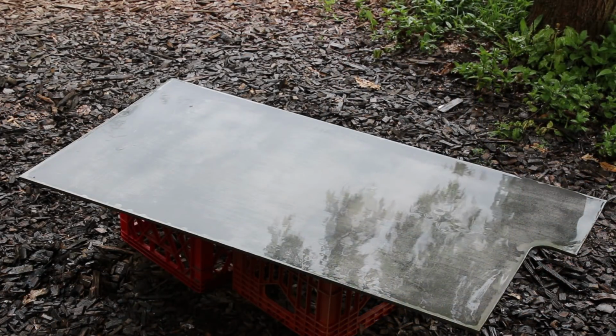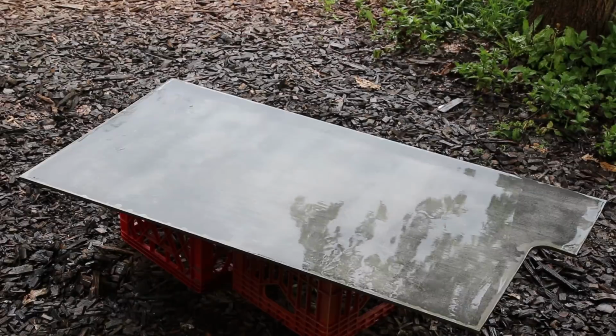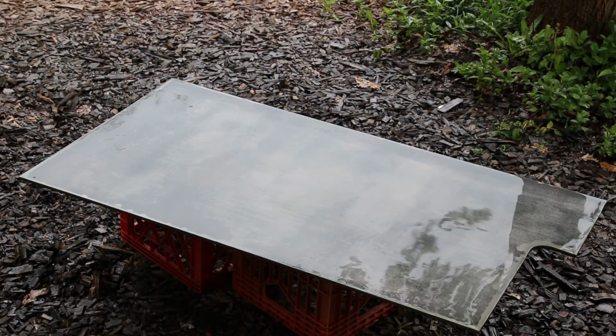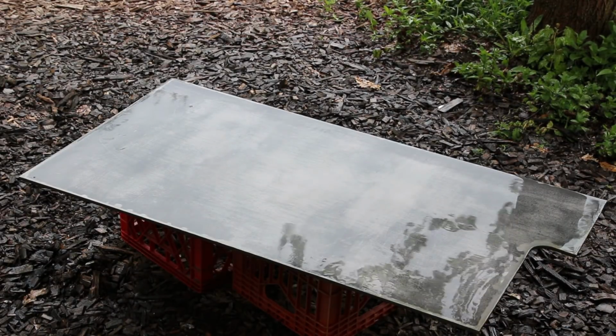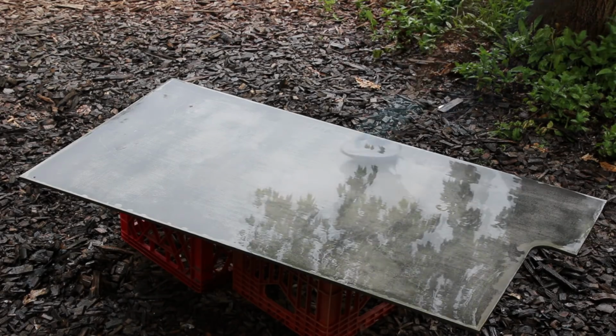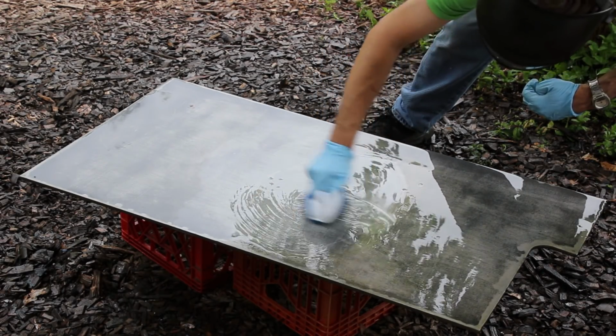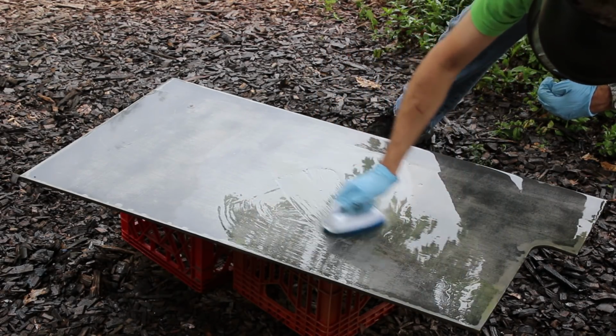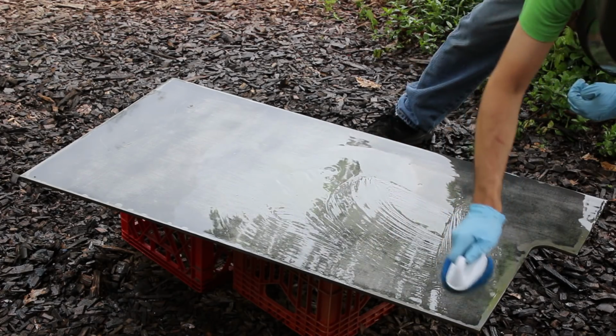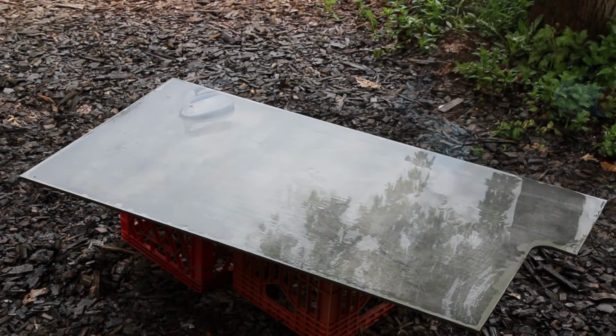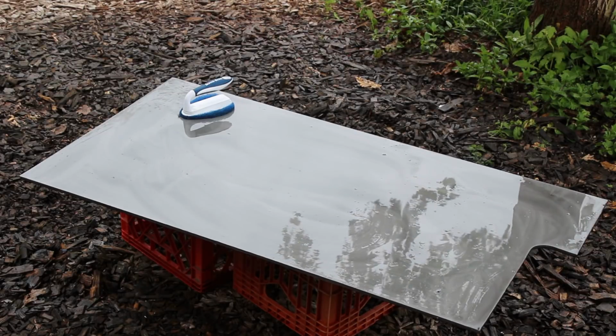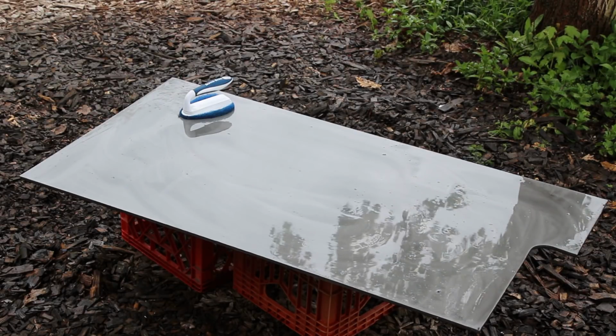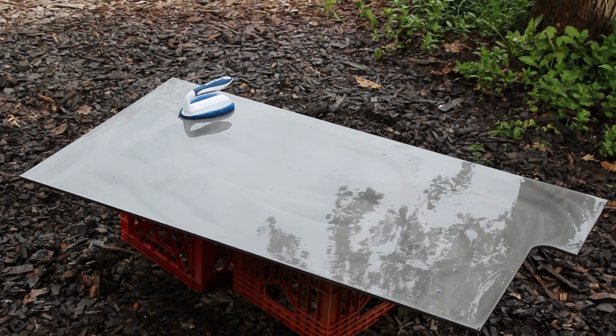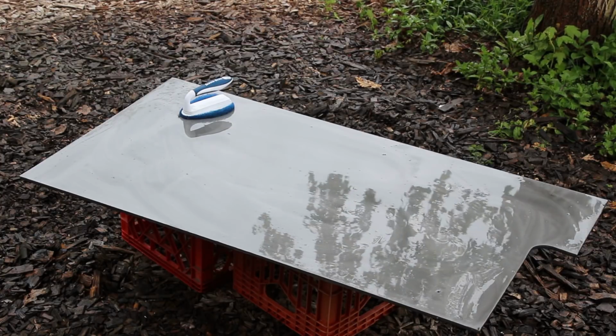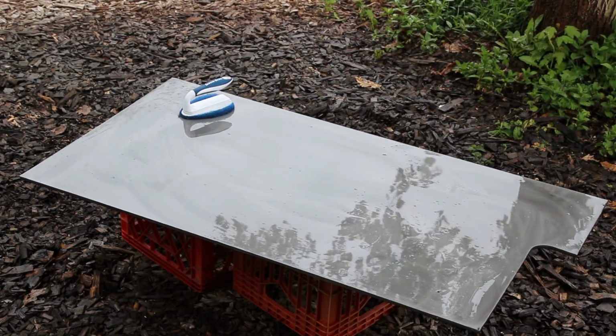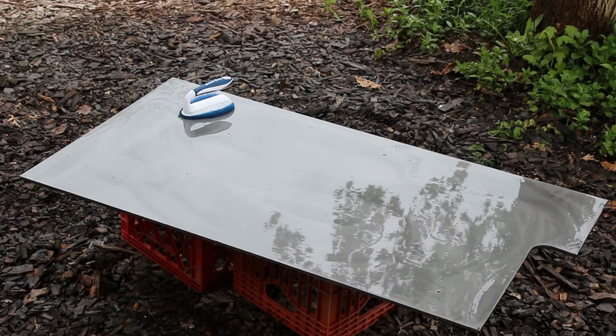Here we are after over half an hour of soaking with the acid, and at some point it seemed that the remaining scale just wasn't really changing. It wasn't coming off anymore. And so I've degreased it again, and now I'm going to hit it again with acid, and I think this time it should take off the rest of it. So all the mill scale has been removed after 2 cycles of first degreasing it with TSP PF, then a diluted solution of muriatic acid for anywhere from 10 to 20 minutes.